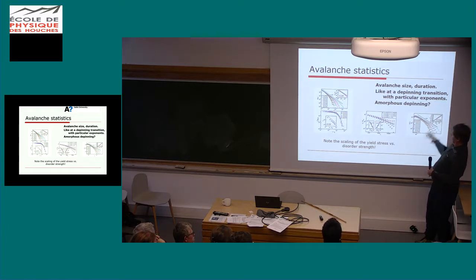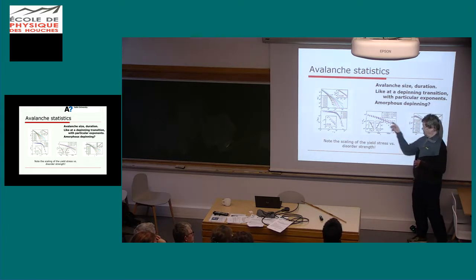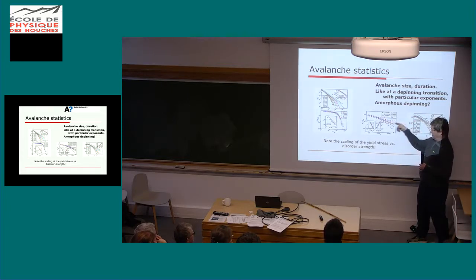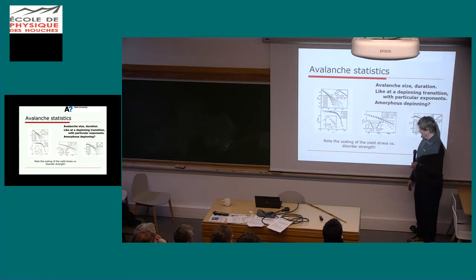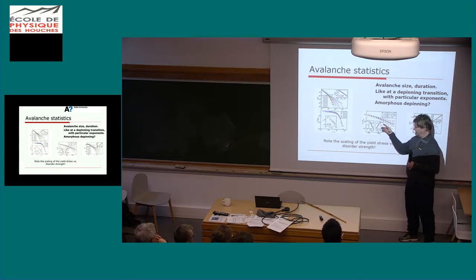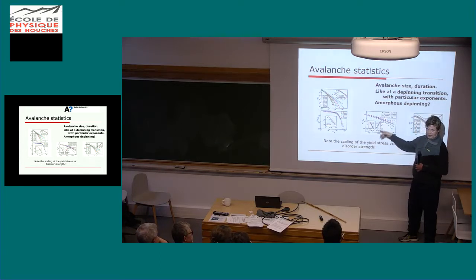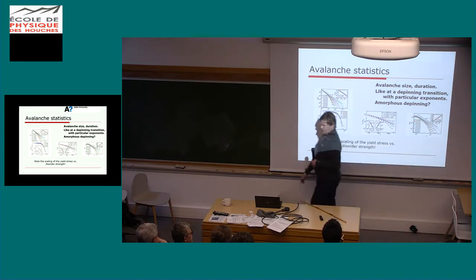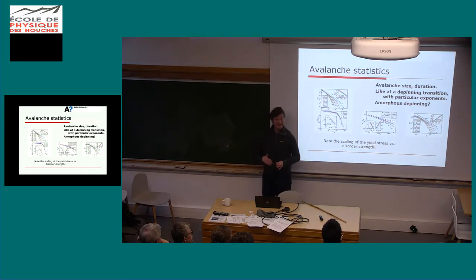That's avalanche durations, but you can also get under-rate creep in such a way that you see a crossover to continuous flow. If you are at large enough stresses, there's a critical point, and if you're far away from the critical point, the power-law decay of the order parameter goes away. One important thing here is how the yield stress scales as a function of the solutes. There's a funny scaling that tells you, if you apply this to real materials, you are seeing fun effects, in the same way that you can increase the yield strength by increasing the strength of pinning or the number of pinning defects.